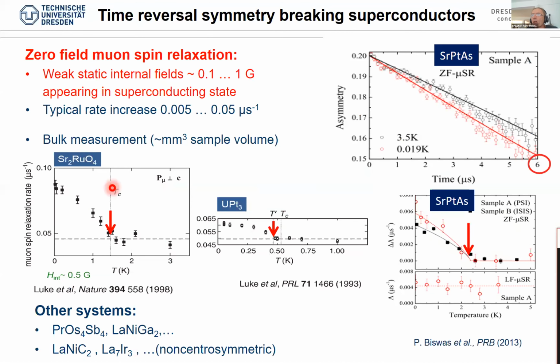And yeah, the old data were already shown by Vadim in the last talk. On strontium ruthenate, the first data were from Graham Luke and co-workers in 1998, where they clearly see an increase of a static relaxation rate below Tc and appearing exactly at Tc. The value is actually small, so the internal fields are of the order of 0.1 to 1 Gauss.